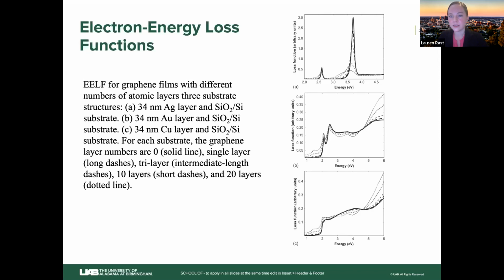Initially, what happens is we reduce coupling to the bulk mode, and the surface mode is virtually unchanged. But then what you notice, after around 3 layers of graphene, is this broadening of the bulk peak. And that corresponds to what you would expect your spectra to look like if you had a deposit of graphite on top.